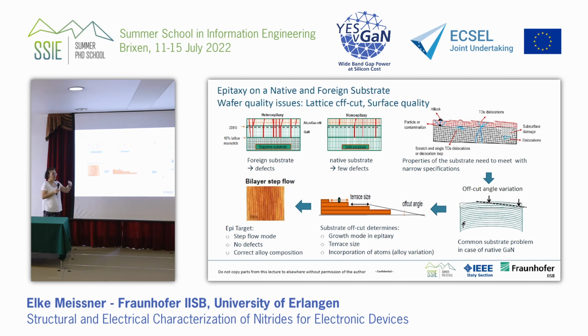But if you now have to adapt the epitaxial conditions, the epitaxy, as I said, reacts instantly on what is offered from the surface. So the epitaxy means that you have an oriented layer in the same orientation, that the layer takes over the orientation of the substrate. And you have to create it by a step flow growth mode over the surface of the wafer. And if you have this, there can be many disturbances. And this is, for example, the off-cut angle. This determines the step flow.